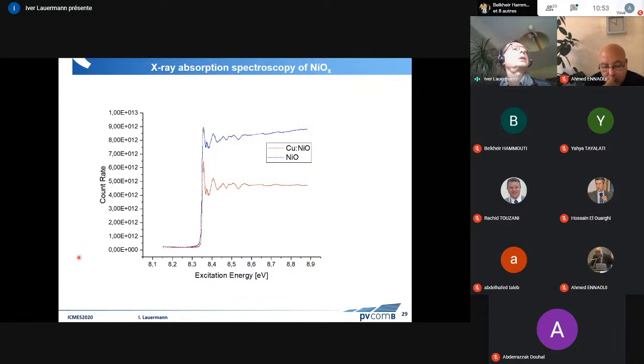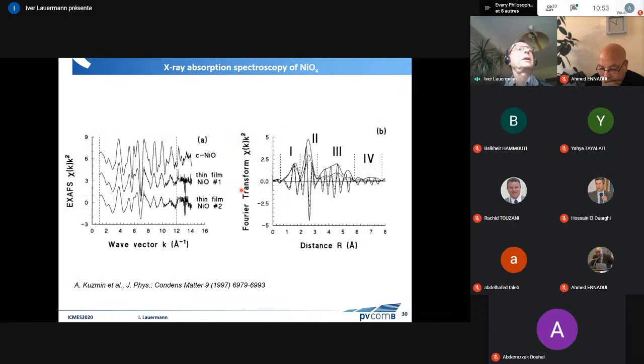Here we see the energy and basically the count rate, which gives you the absorption coefficient of the material. And from this fine structure, we can determine the structure, especially the distance between the next neighbors in the material that we're looking at. I cannot go into the details, but this is a very interesting material to see the differences between different preparation methods, in this case of sputtered nickel oxide.